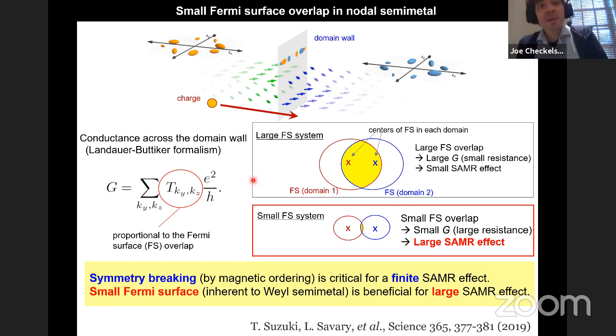electronic structure, because then if you consider in real space a magnetic domain, which you have when you go from one magnetic domain to the other, in real space you have a different magnetic pattern. But in K-space, because this is a Weyl system, the position of the nodal part of the electronic structure is different in those two real space domains.